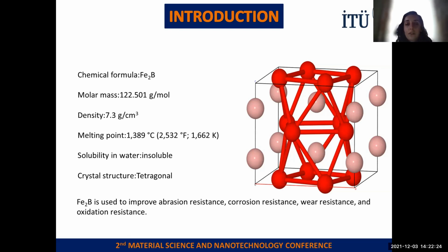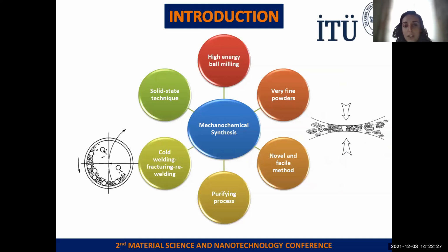For this study, we try to synthesize these iron boride nanoparticles using solid state reactions. Mechanochemical synthesis is one of the solid state reactions. It is based on cold welding, fracturing, and rewelding of the raw materials. Using the high energy ball mill, heat occurs and these raw materials are transformed to the boride phase, mechanochemically synthesized using the high energy ball mill and solid state reactions in the high energy ball mill environment.